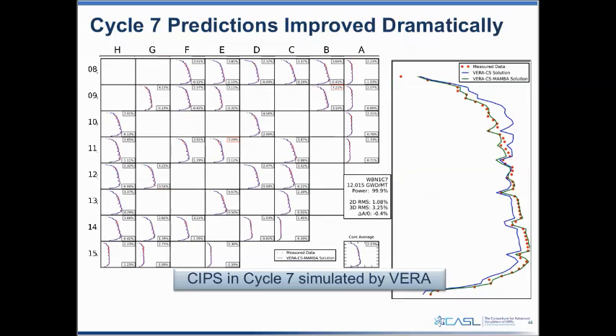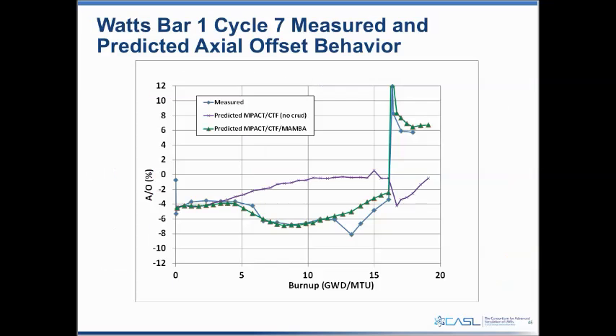But you can also see then we did simulate the removal of crud there, and we match that big jump in axial offset around 16,000 megawatt days per metric ton as well. So overall, this is quite a good result in terms of trying to simulate cycle 7 of WattsBar Unit 1.